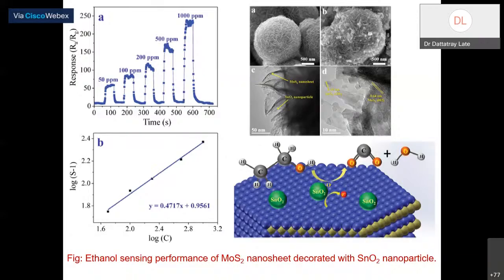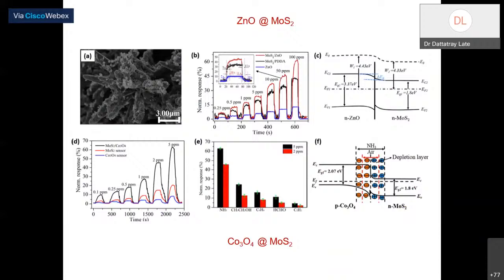And this gives basically a very high surface area. Because of the high surface area, for example, we tested here the ethanol sensing performance of the MoS2 nanosheet decorated with SnO2 nanoparticles. And with another material, for example zinc oxide on MoS2, this has given a very important result. Again, it can go down to just 0.2 ppm level.